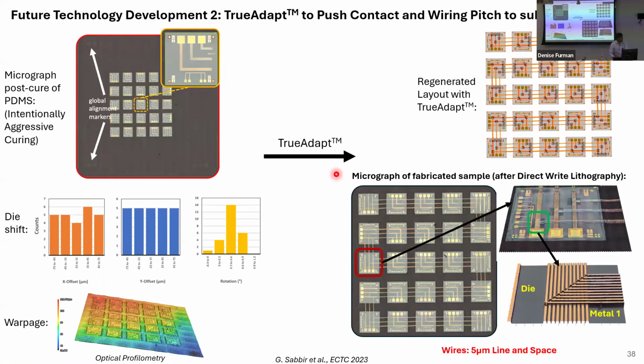So here are some very early experimental demonstrations of this kind of approach. Here you see a micrograph of a 5x5 array of dies that are embedded in PDMS. And these were cured aggressively at a high temperature so that the dies have a significant shift. So you see these are the histograms of the die shifts as well as the warpage. And then what we do, using the TrueAdapt process, this is the actual regenerated layout for the shifted dies. And then we use the maskless lithography tool to print these new interconnects that now successfully connect the wires on the die. And using this approach, we can push the interconnect pitch down now to 5 micron line and space from the original 20 microns.